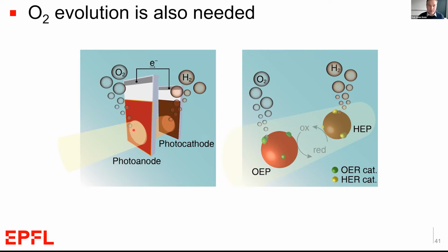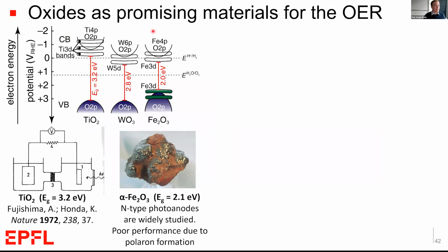The most popular materials that have been developed are these oxide semiconductor materials. In fact, the first material ever shown was titanium oxide for overall water splitting. But again, the band gap of titanium dioxide is too large, so it only absorbs the UV light. Iron oxide and tungsten trioxide absorb more light given their smaller band gap. And in particular, this iron oxide material has been widely studied, also by our group, but is quite difficult to get to work well due to this poor electron and hole transport given this polaron formation.